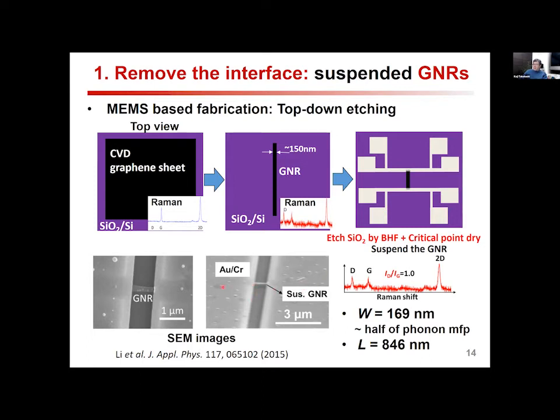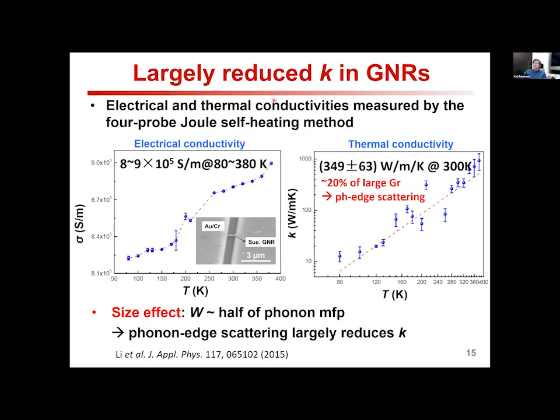Its size, and especially the width, is 170 nanometers, almost half of the phonon mean free path of large area graphene. And we obtained the thermal conductivity of such a suspended graphene nanoribbon. This is our data. The thermal conductivity of suspended graphene nanoribbon shows 350 watts per meter Kelvin at room temperature. This is only 1/5 of large area graphene, mainly due to the phonon edge scattering.